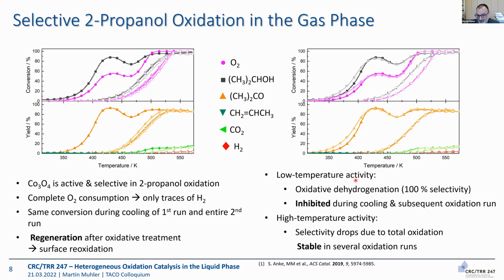So low temperature activity, oxidative dehydrogenation, 100% selectivity to acetone. It's then inhibited during cooling and subsequent oxidation. And this high temperature channel, that is rather stable. We can go up and down in temperature as often as we want. And here we are then a bit less selective. You see here, so there's also CO2 included at the high temperatures. We do form some CO2.